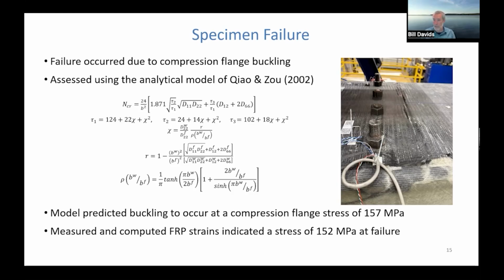If you just straight up take nominal properties of the girder and do a laminate analysis and input those properties in, it's 157. We computed FRP strains at that first failure of 152. And those computed strains are going to be quite accurate because remember, we also measure strains in the girder, in the bare girder cross section, and we can compare them with computed there. This section is essentially linearly elastic. MC over I does a very good job of telling us what's happening. So this is excellent agreement between what we actually saw and what we would have expected.